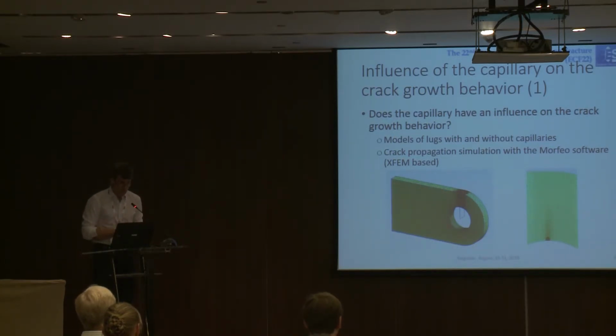And to do that, we have done a crack propagation simulation with the Morfeo software, which is an XFEM-based software. With XFEM you have fewer problems with the meshing, but it remains a FEM-based method, meaning that you have to work on a converged mesh. And to have a converged mesh, you have to be sure that your mesh is fine enough in the region of your initial defect. I forgot to mention, but the initial defect is always the same in all the load cases we have computed, namely a part-through crack in that upper region. And this is why you see that the mesh is so fine in that region.